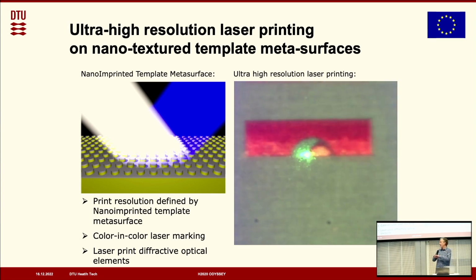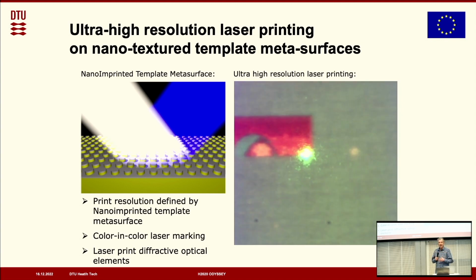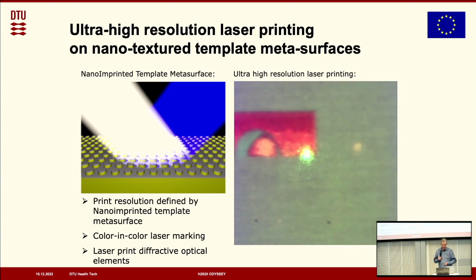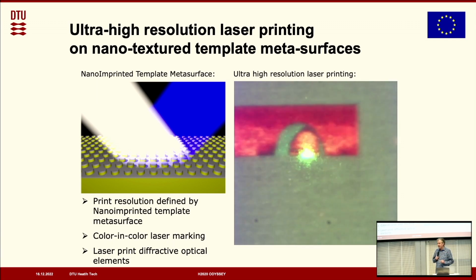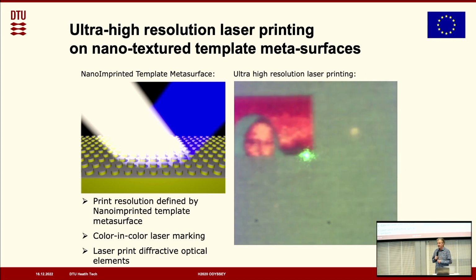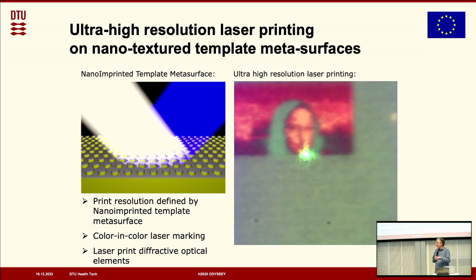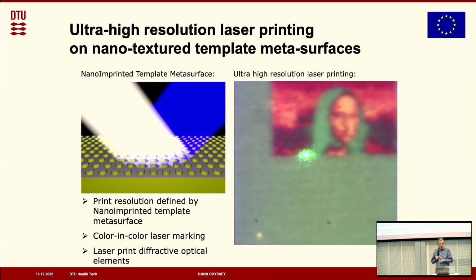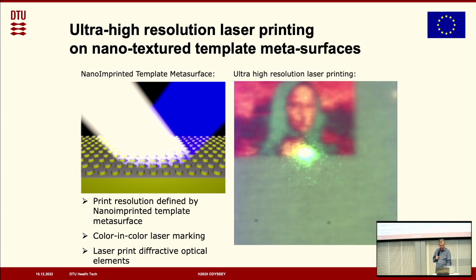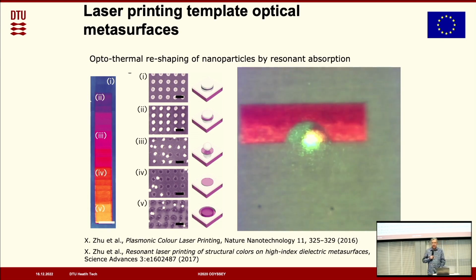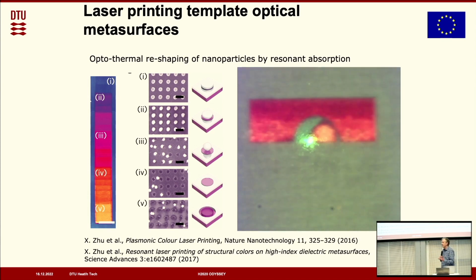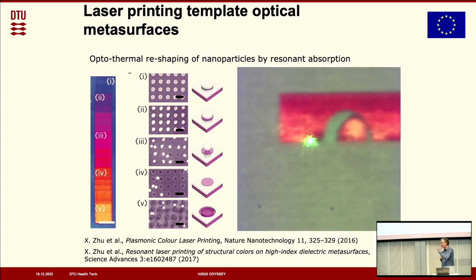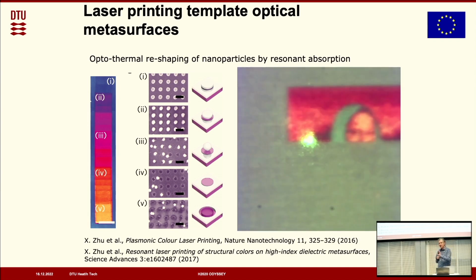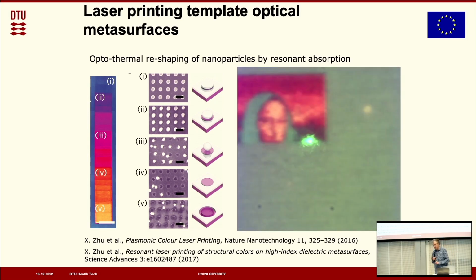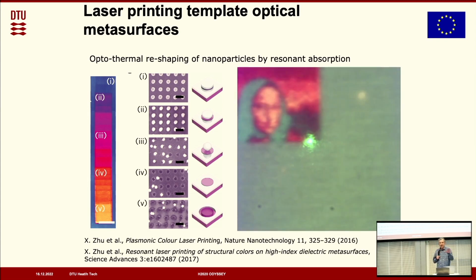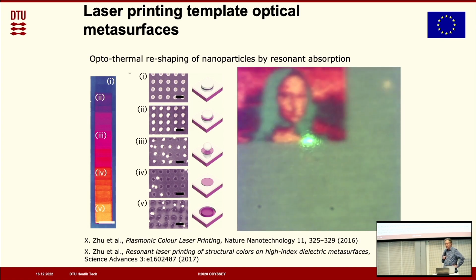So we take something which is homogeneous, this homogeneous blue surface, which we can make in large quantities and cheap because they're identical. So we can just print them and then we can give it a functionality. In this case, it's a color image by using this so-called resonant laser printing. You can also say that what we're doing is that we are creating a laser printer system where we are laser printing on a special type of paper, just like these thermal printers that you use in the supermarket when you get your receipt from the cashier. There's no ink in that printer. The ink is sort of built into the paper. Here, our paper is then this nanotextured isotropic surface. And then how can it be that we create different colors?